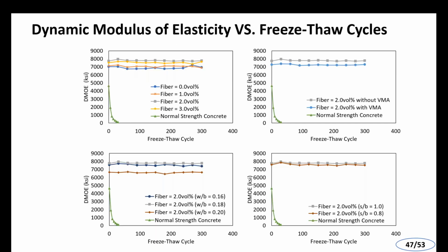This graph shows the dynamic modulus of elasticity after several cycles with the various designs of UHPC being used at the university. The normal strength concrete is just not there. That green line you see was damaged very quickly. We'll admit that air entrainment wasn't placed on those particular samples, but they were just used as a reference for UHPC. The UHPC for the most part shows excellent behavior in terms of frost attack, largely because there's not a lot of water available in the interior of the concrete to cause that cyclic freezing expansion internally.